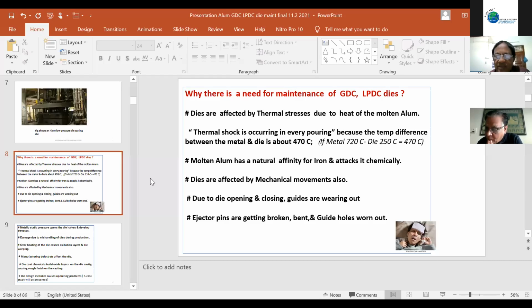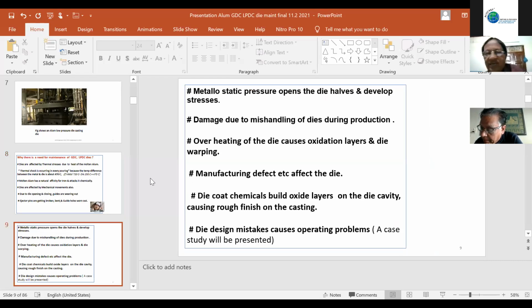It affects it. Molten aluminum has a natural affinity for iron, and it attacks it chemically also. The dies are affected by mechanical movements also. Ejector pins get broken or bent, and guide holes wear out. So the die is affected by so many factors. Metallostatic pressure opens the die halves and develops stresses. However much you close the die, it opens at the top.